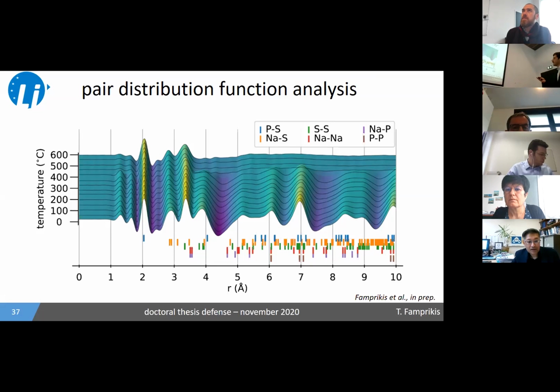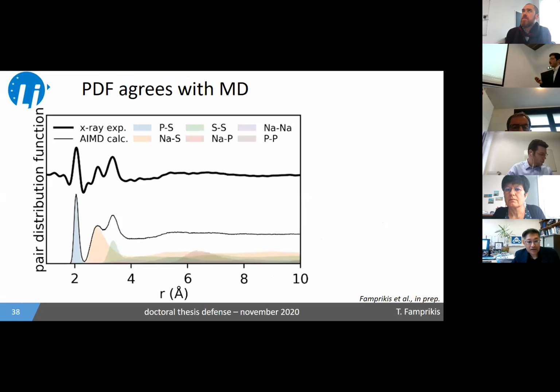So it's quite unintuitive and it took me a while to understand, but a key way to convince you and me that this is not an artifact is that we can take the molecular dynamics simulations that I showed you before, and extract the corresponding pair distribution function from the simulation. You can see we get a perfect agreement. In fact, we have only the first three sharp peaks shown on the bottom for PS, SS, and NaS.